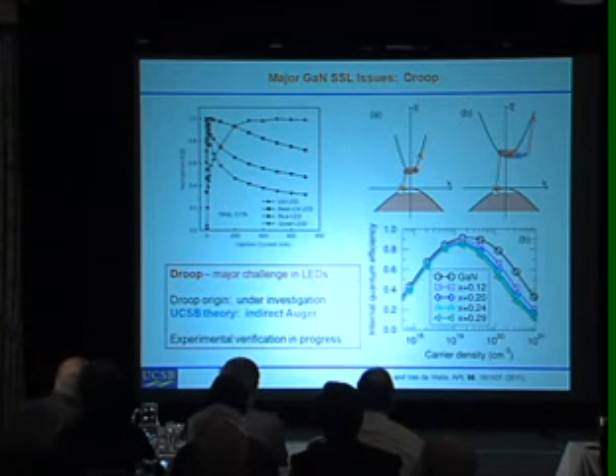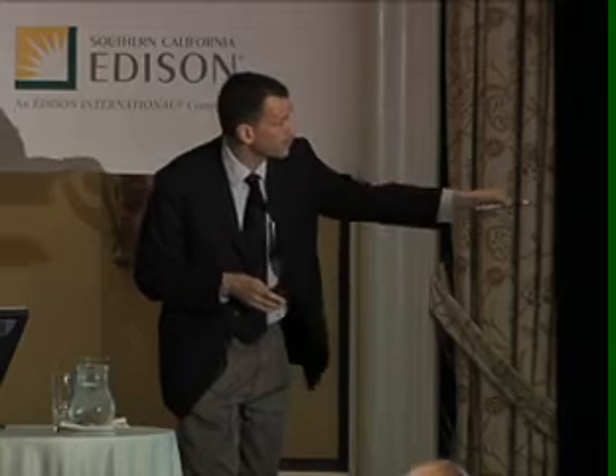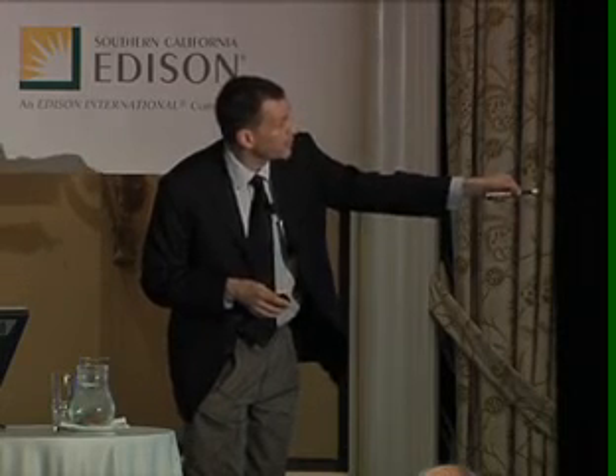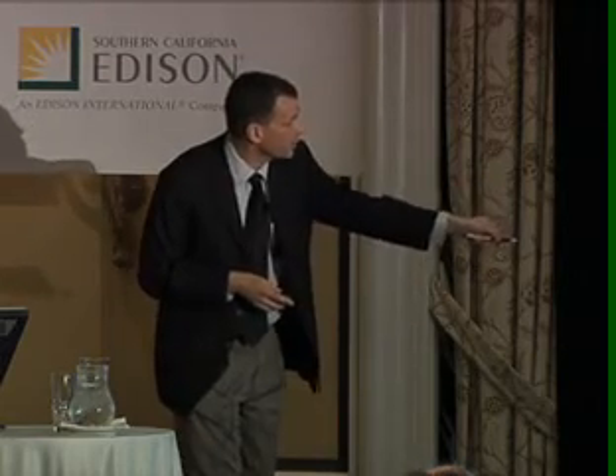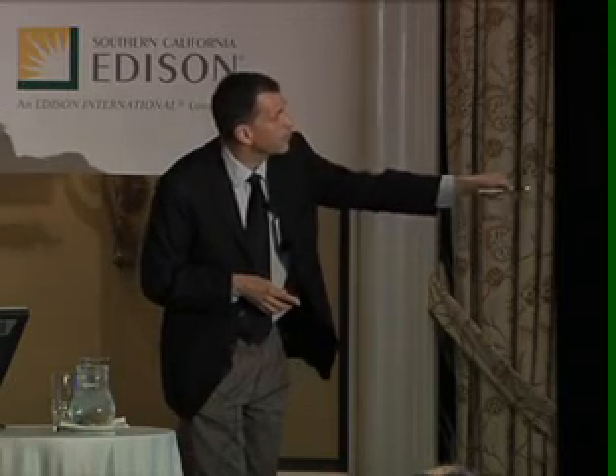where he's done fundamental density functional theory calculations of this 3-body process. So these are actually very challenging calculations, and actually predicted fundamentally that a phonon-assisted, or what's called indirect Auger, is the cause of droop. Claude Weisbuch and I have experiments underway to see if we can get a direct experimental signature if indeed this indirect Auger process is a cause of droop.